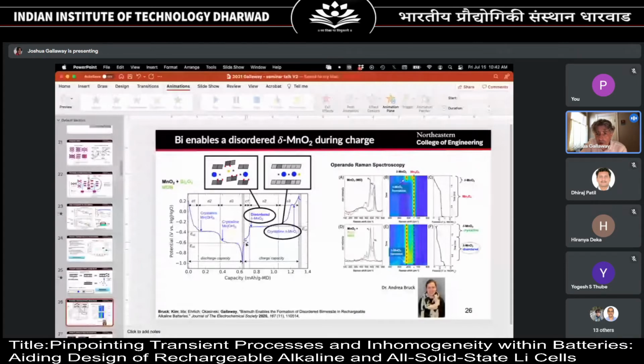But here, if we have the bismuth in there, we see two peaks from the very beginning. And these are both there all the way through the charge. And these two peaks show us that the layered structure is there throughout the entire charge. And without the bismuth, it's not.